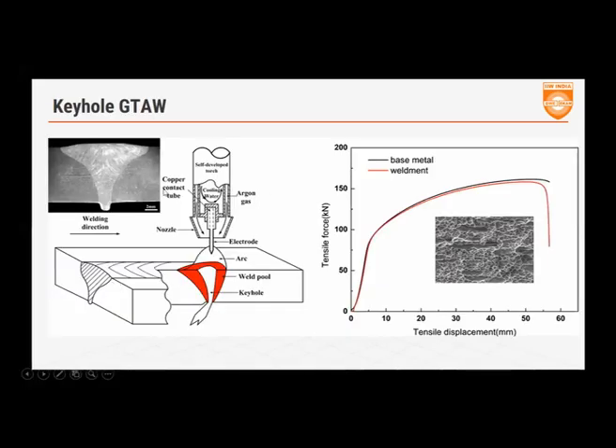This is the kind of cross section you can expect. We'll see much more when we move forward. Just to give you a schematic idea, 2 plates, butt joint put together. When you start welding with the GTAW process, the arc becomes very concentrated. Because of the concentrated arc, it creates a keyhole throughout the thickness. The plasma and the gases are released from the bottom. And when you move in the direction at a high speed, the pool is continuously held on its own. You don't need a backing layer at the base. It works without it, and it forms a typical wine glass profile for you. No edge preparation was required to do this.